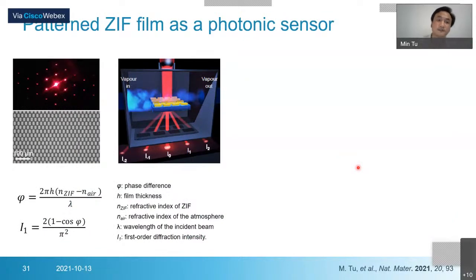With this patterning, we did some demo of our patterned MOF film, using it as a photonic sensor. We have this MOF patterned periodic structure. When we irradiate the film with a red laser, with visible light, it's kind of like single crystal diffraction, but here we use visible light instead of X-ray. So we have visible light irradiated on the periodic structure, then we have the diffraction spots you see here. According to this equation, the first order diffraction intensity is related to the phase change, and the phase change is related to the refractive index change of the pattern. If gas molecules go into our MOF pores, then the refractive index is changed, and we can see the first order diffraction intensity will also change. So by using this scheme, we can do gas sensing.